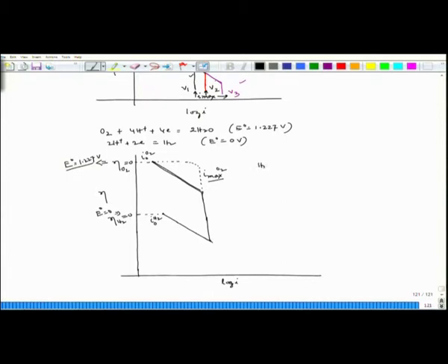If I consider the H plus ion diffusivity, DH plus, and DO2, then DO2 is actually less than DH plus. Correspondingly, I max for the O2 reaction should be less than I max for the H plus ion, considering that delta and C0 are fixed. Of course, temperature is also fixed. I am just considering the size of those molecules. Since the H plus ion is very small, its diffusivity would be very fast. In that case I max should be high for the H plus ion.